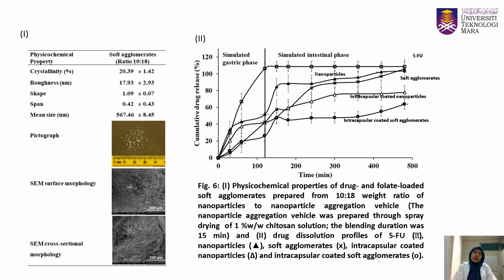So, the main finding is that soft agglomerate is a must because it is more responsive to intracapsular coating by sodium alginate, for whatever material that you use for nanoparticles. And this can further decrease the drug release through soft agglomerates and intracapsular coating.